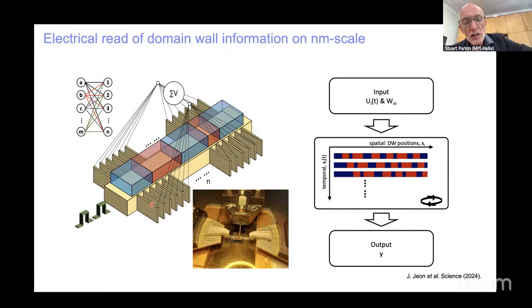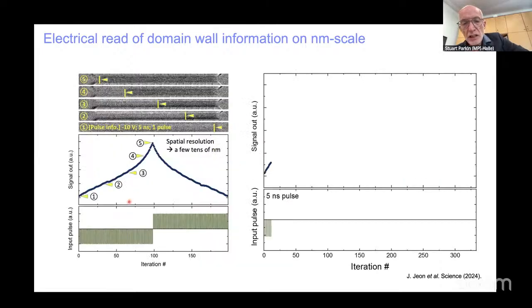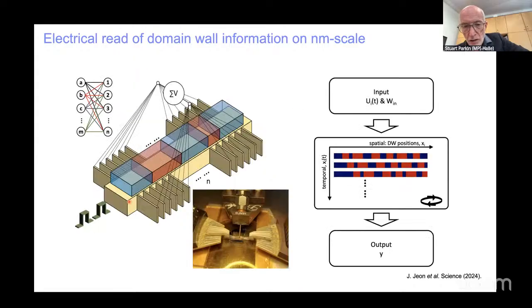And on the edges, these yellow regions are electrodes, which we designed by electron beam lithography so we can measure locally the transverse Hall voltage. And in the devices I want to briefly show you, we have 16 of these Hall sensors designed from the platinum underlayer. And a very important point is, in this cartoon, you may notice that the width of the magnetic racetrack is narrower than the width of this platinum underlayer. And this is by design. So it turns out what we discovered, as shown in the next foil I'm going to mention, is go back.